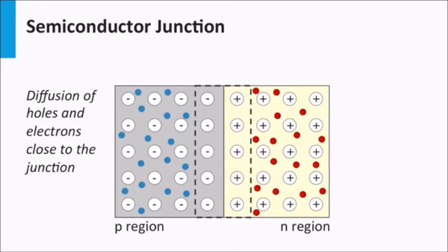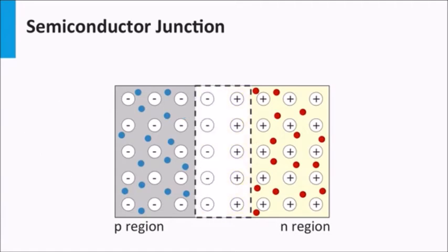The same is valid for the electrons. As the diffusion length of electrons in p-type is short as well, they will soon recombine with one of the majority holes. As a result, there is a small region around the p-n interface in which all charge carriers are wiped out. In this region, the only charges present are the charges related to the background, donor and acceptor atoms.